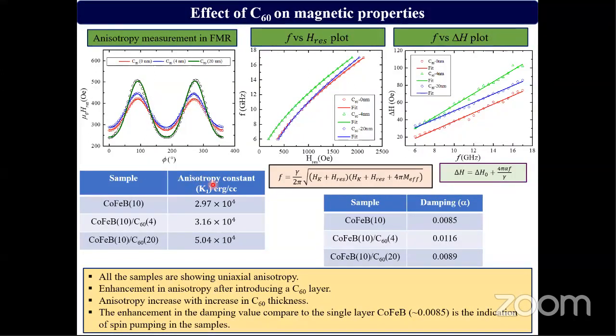We have also calculated the anisotropy constant for the samples, and for cobalt iron boron 10 nanometer, the anisotropy is 2.97 into 10 to the power 4, and for cobalt iron boron C60 4 nanometer, it is 3.16 into 10 to the power 4, and for 20 nanometer C60, it is 5.04 into 10 to the power 4. So introducing a C60 layer, the anisotropy is enhanced, and also when we increase the thickness of the C60, the anisotropy is also enhanced.